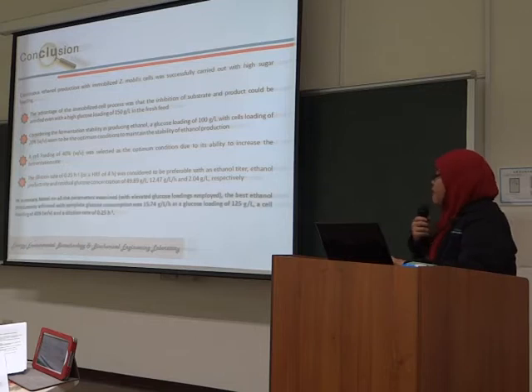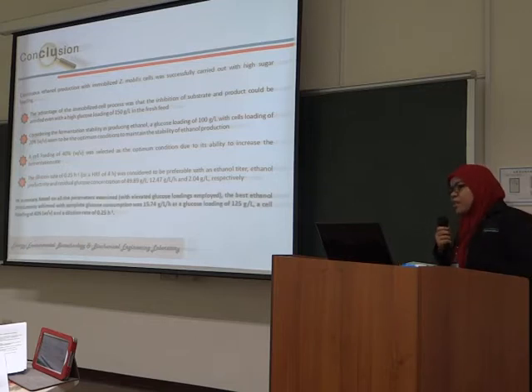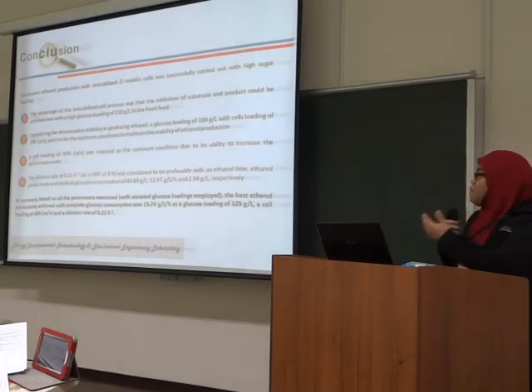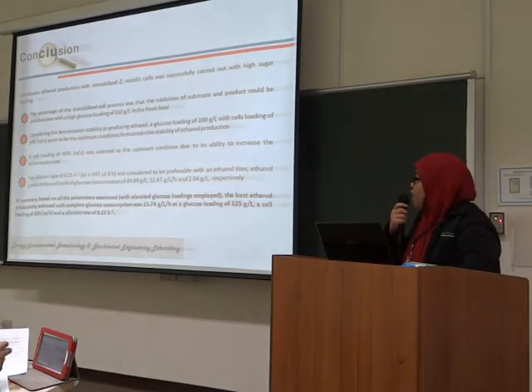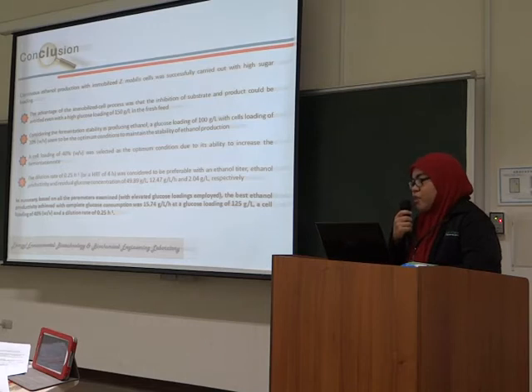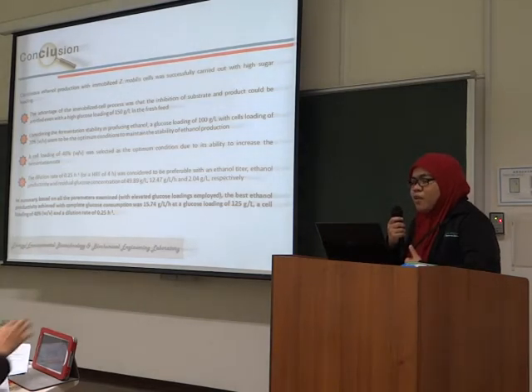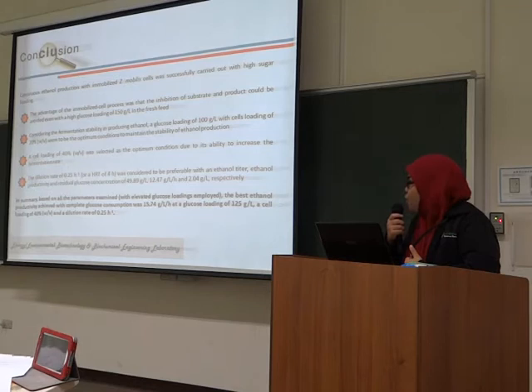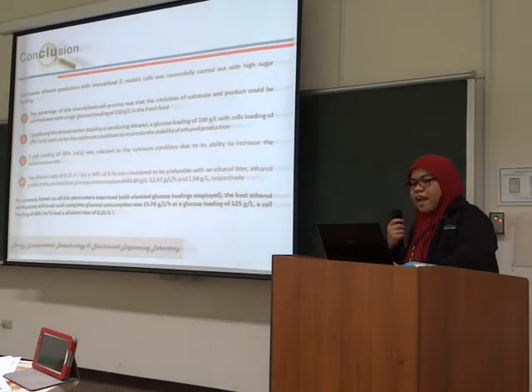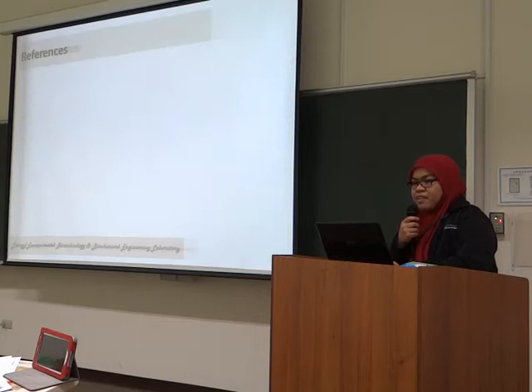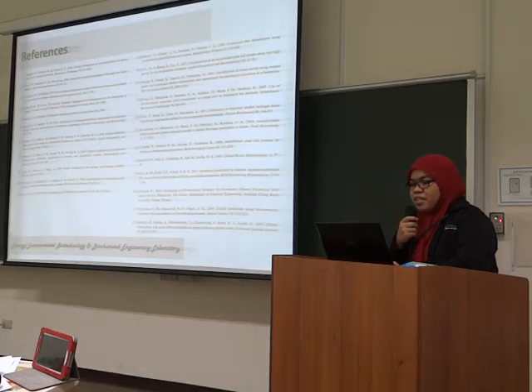And in summary, after I tried to increase the initial glucose loading, I got the best ethanol productivity with complete glucose consumption at initial loading 125 gram per liter, with the productivity 15.74 gram per liter per hour, cell loading only 40% weight per volume, and dilution rate only 0.25 per hour. And I think this is my reference when I do this study.